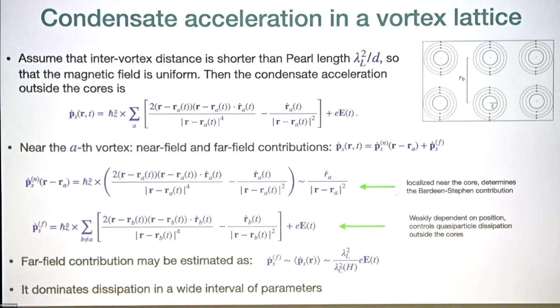And so the main message is that the near field contribution, which is peaked near the core, if you plug this contribution into our formulas, you essentially recover the Bardeen-Stephen result. And the far field contribution creates a new contribution to dissipation, and it dominates in the wide interval of parameters.